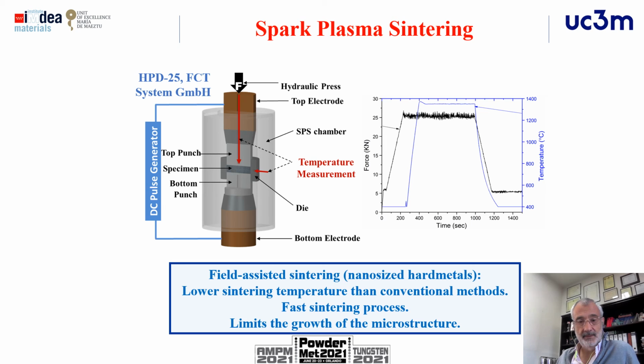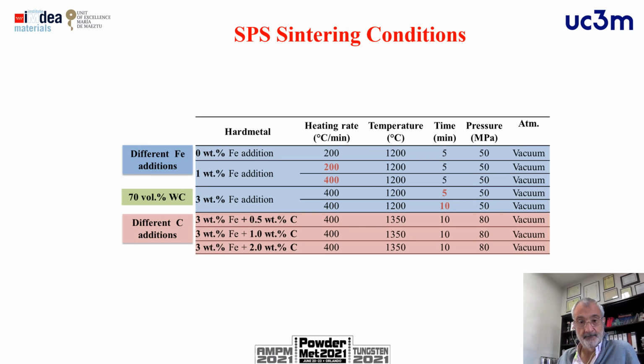Here we can see the spark plasma sintering method. Here we have the typical force temperature time diagram, and with the field assisted sintering, we use much lower sintering temperatures than the conventional sintering temperature. So in principle, this will avoid the grain growth of the tungsten carbide. It's a fast sintering process. We can, in this way, obtain a much more proper microstructure, looking for a good final fracture toughness combined with good hardness. We have tested many spark plasma sintering conditions.